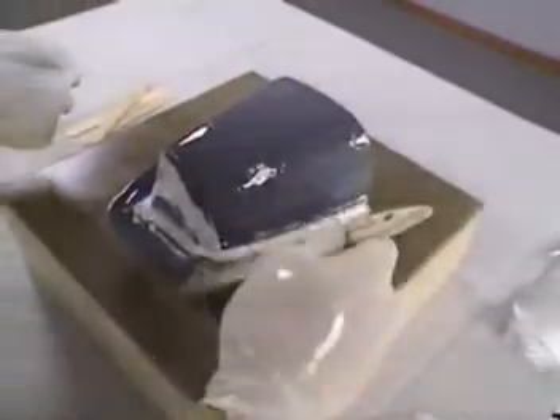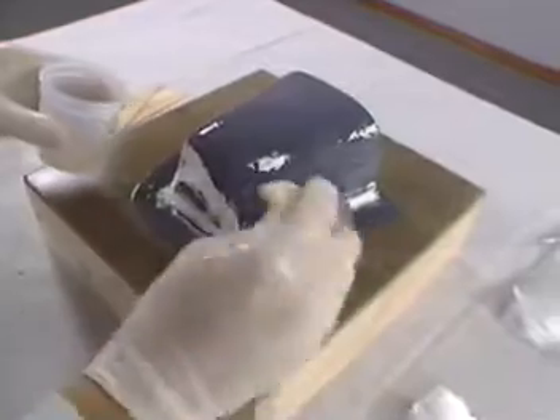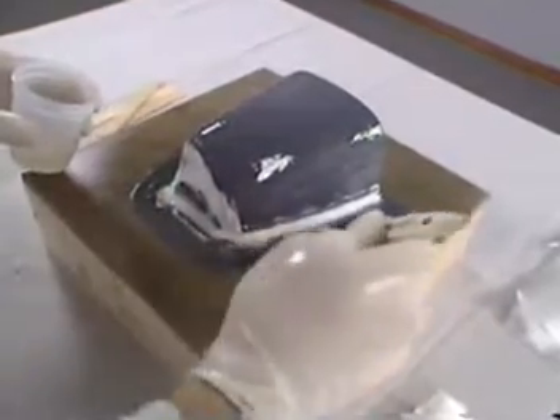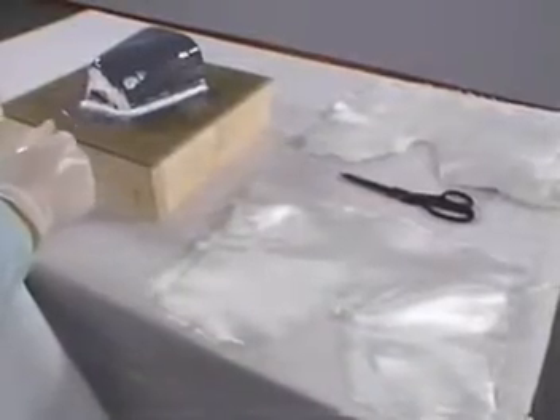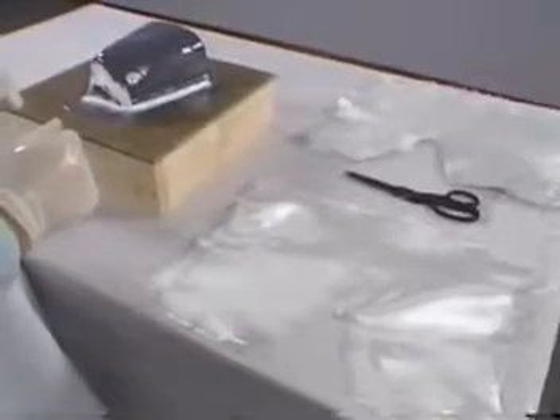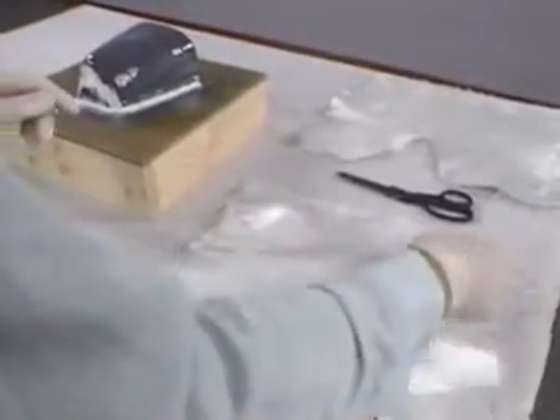After the base resin coat, he is ready to begin laying in his layers of reinforcement. Dennis has pre-cut the layers of reinforcement he will need. This avoids the need to count layers as they are applied and saves cutting time after the resin is mixed. For this mold, Dennis will use 4 layers of 2-ounce fabric and 8 layers of 6-ounce. Remember that the mold should be at least 3 times thicker than the parts which are to be pulled from it.